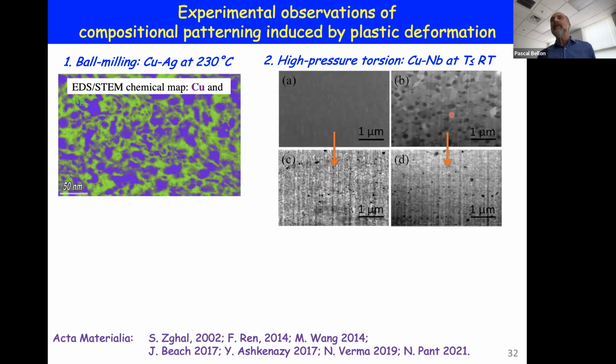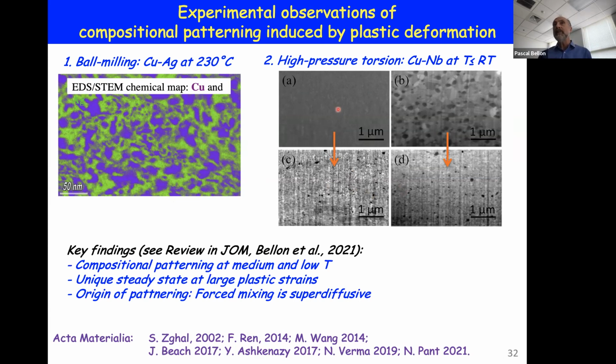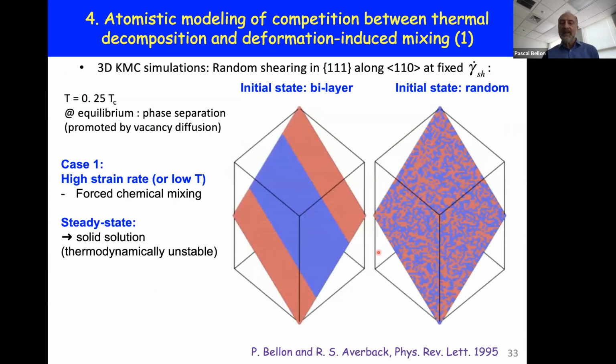Whether we start from a solid solution or from pre-existing precipitates, using high pressure torsion at very high plastic strains, we get the same number density and size of nanoprecipitates, whether the initial microstructure had precipitates or not, or whether those precipitates were too big for the steady state size. If you're interested, last year we published a review on patterning in systems subjected to plastic deformation in JOM, and I would encourage you to look at this issue. And here, just to give you a flavor of how the self-organization proceeds.